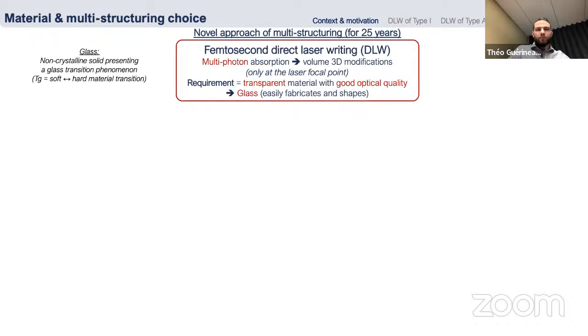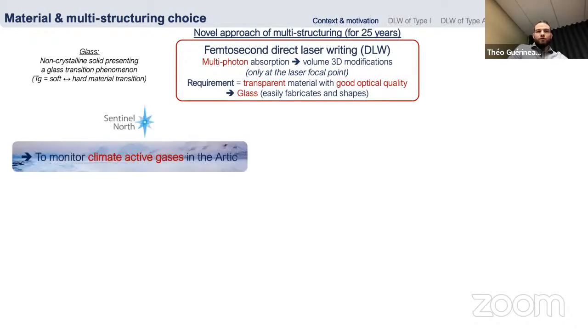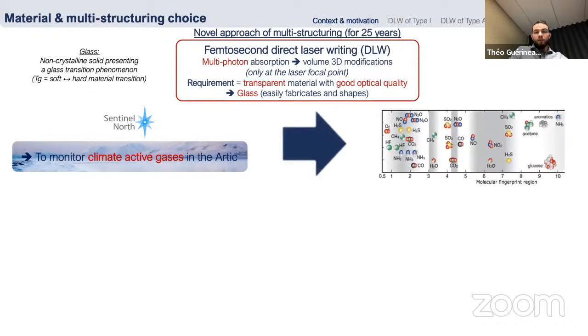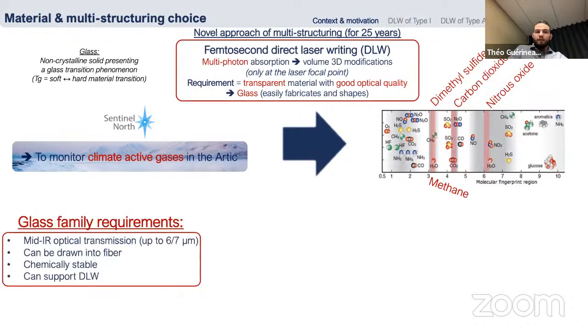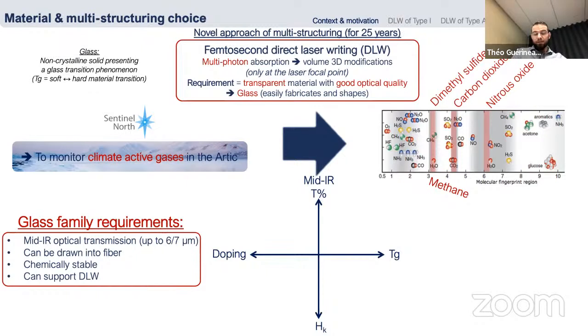I think everybody knows the definition of glass, but through the Sentinel North program, we want to monitor some climate active gases in the Arctic. If we have a look at this very interesting graph, you will see that above 3 micron, we have the fundamental absorption of dimethyl sulfide, methane, carbon dioxide, and nitrous oxide. So that means that our glass family should have a mid-infrared optical transmission at least up to 6 or 7 micron, can be drawn into fiber, is chemically stable, and can support the direct laser writing process. So this graph represents 4 properties.